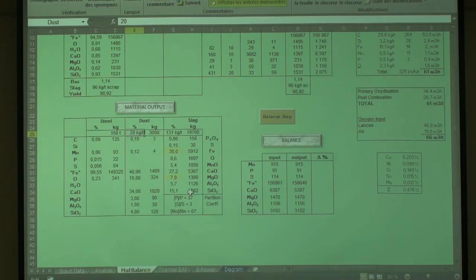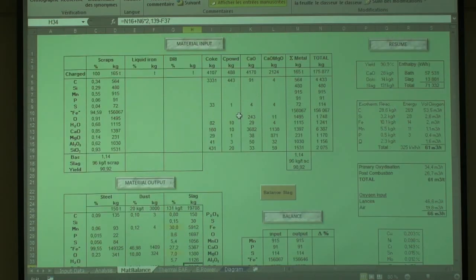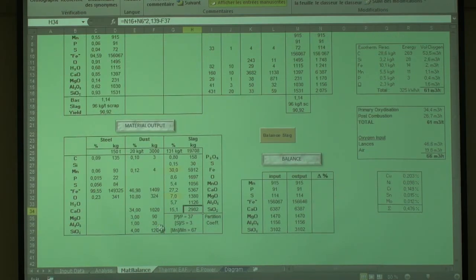So the first step in the calculation for slag is the SiO2. The SiO2 is calculated by the amount of oxide which is charged from the scrap, plus the silicon which will be oxidized. So here you have N16. This is the SiO2, N6 is the silicon times 2.139. This is to convert Si into SiO2. Yeah? Minus the silica which is consumed by the dust.